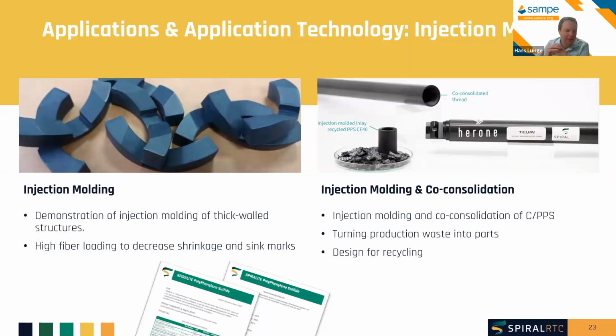If we go further to the application and application technology, starting with injection molding compounds, I'll just show some examples, and maybe for you to get a feeling of what is possible, and maybe get some inspiration out of this, I hope. So it's injection molding compounds of highly filled fiber materials. In this case, it's a carbon fiber PPS. Really with the aim to decrease shrinkage and sink marks. So these are thick wall structures, and typically if you do that unfilled, you get some sink marks, and that's absent in these kinds of materials.